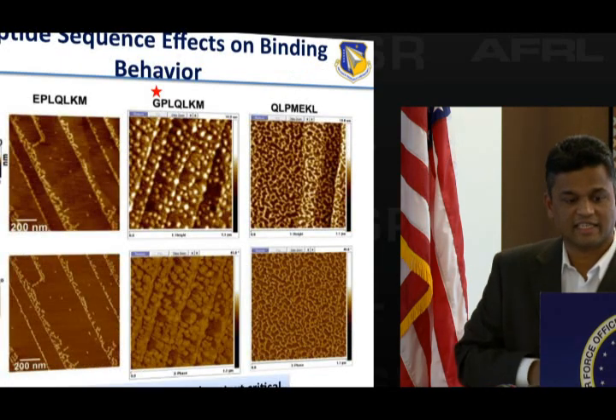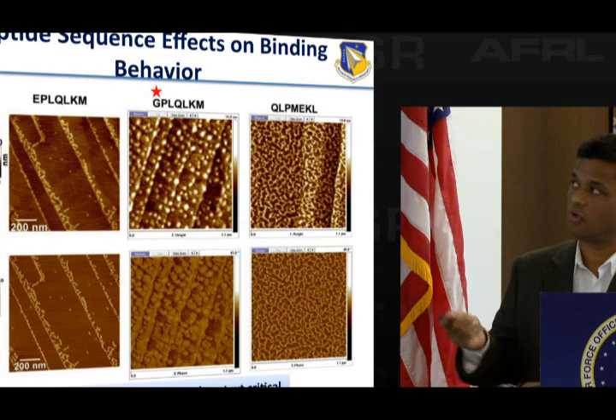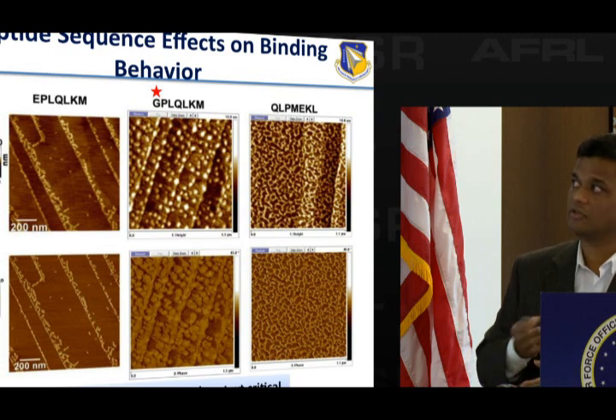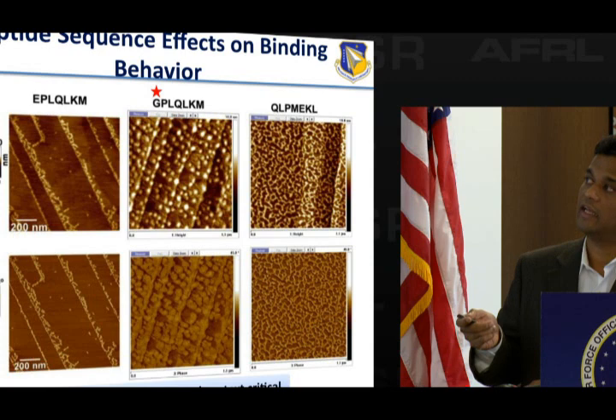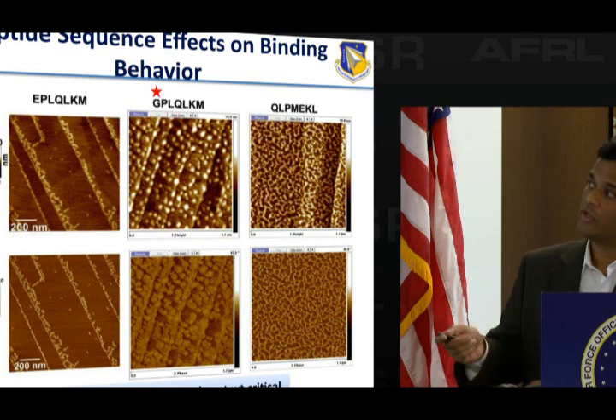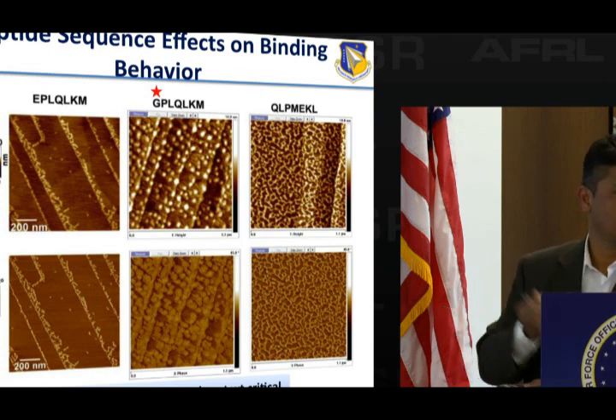What is interesting is that if I took that sequence, this is one example, this is amino acid in single amino acid code. This is a 7 amino acid peptide. And I started to play with it a little bit. If I knock this one out, this glutamic acid, if I pull it out and I put a glycine in place, which is a small amino acid, remove that charged residue away, you can see now the morphology of that binding event on the graphene surface is completely different. Okay, so that tells you that amino acid is required for that edge binding.